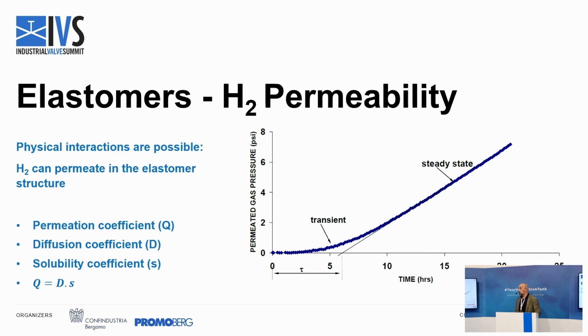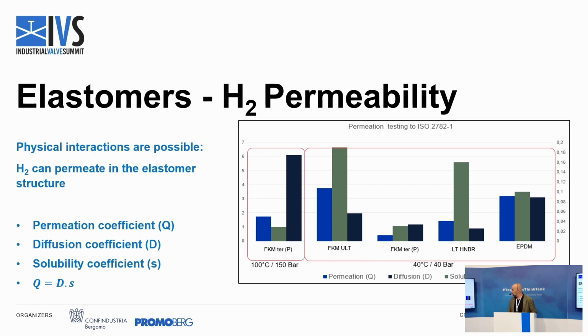And this brings us to ask if hydrogen also has a physical effect on the elastomers, can cause swell or other. It actually doesn't cause swell, but the permeability is not zero. So we actually have hydrogen that permeates in the elastomeric compound. Again, we ran some tests. We also tested the best compound at different temperatures, and we saw that the permeation is quite low. So we are not worried. We know that the sealing itself is not an issue. The permeation is not that high to create a leakage.